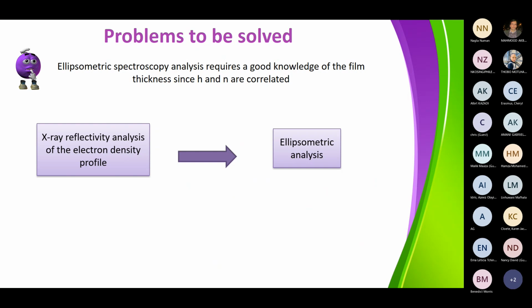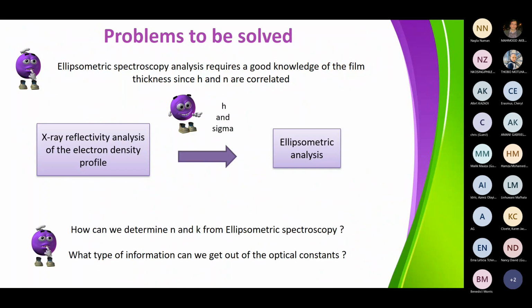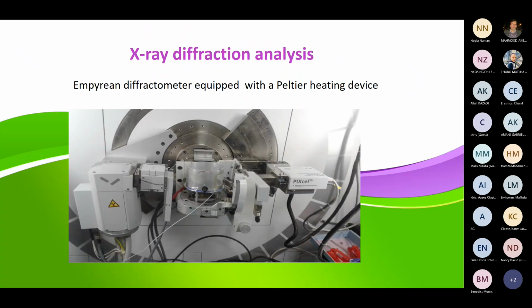In ellipsometric spectroscopy, as Guillaume is going to show you, one major concern is the fact that if you really want to get the good information, you need to discriminate between the index of refraction and the thickness of the film. And if you don't know very well the thickness of the film, then that's going to be very difficult to get a good estimation of the refractive index. So what we do is X-ray reflectivity measurements. We measure the thickness, and once you have done that, you can determine by ellipsometric spectroscopy the refractive index of the material. Okay, fine. So I'll start with the X-ray diffraction analysis.